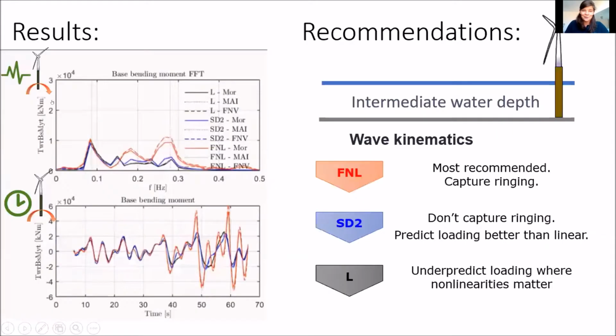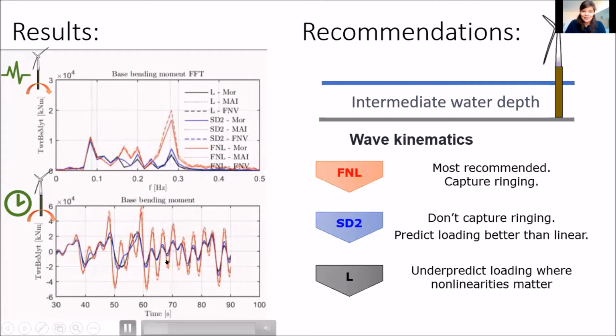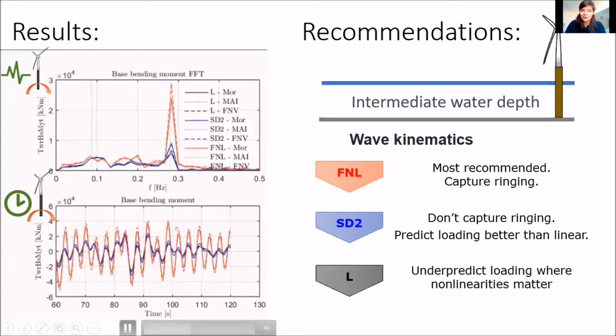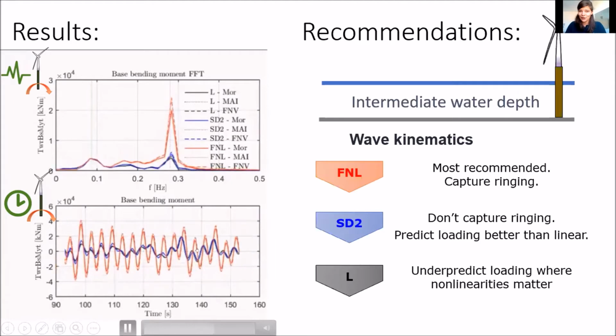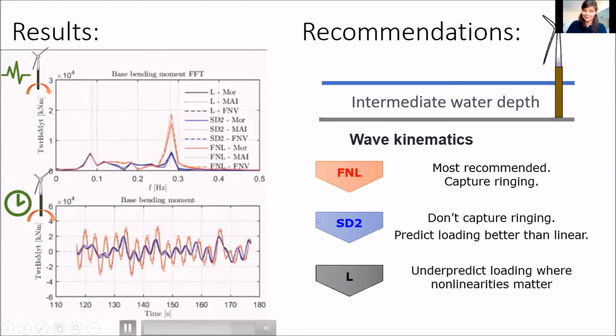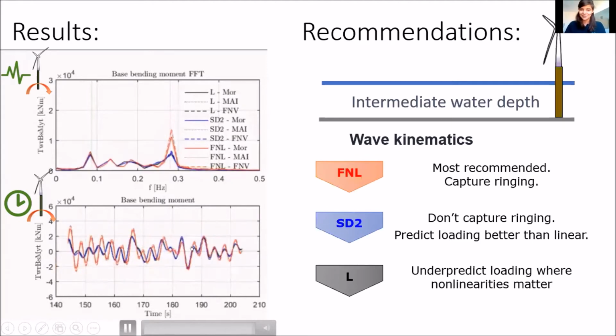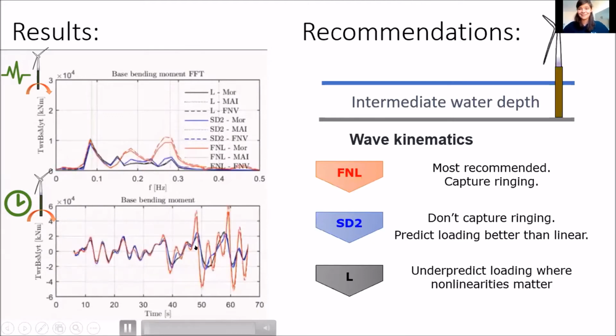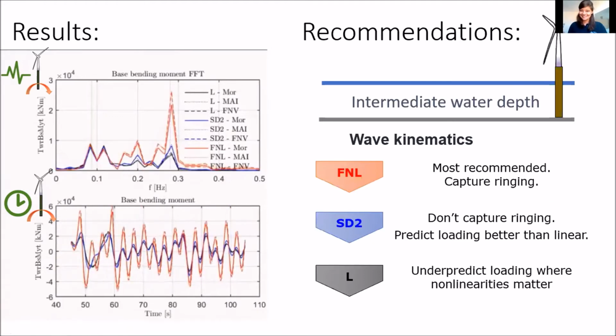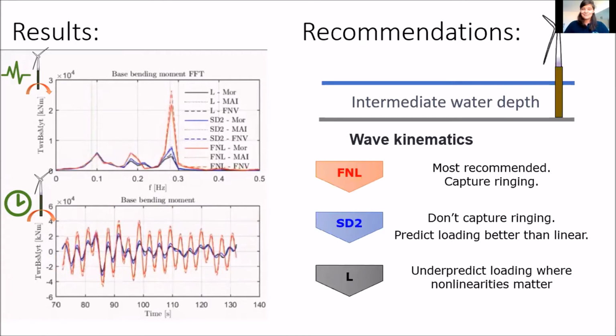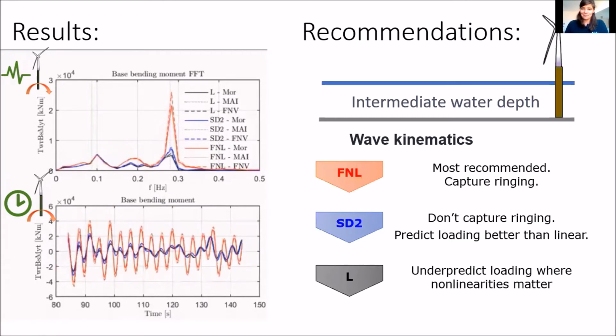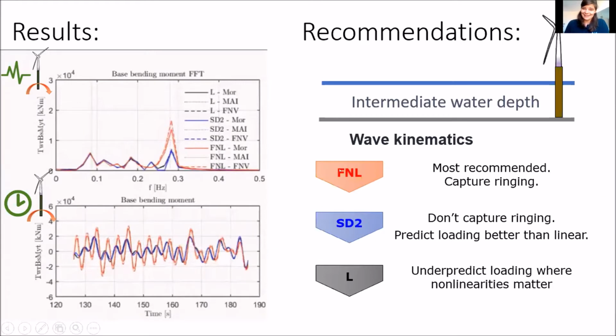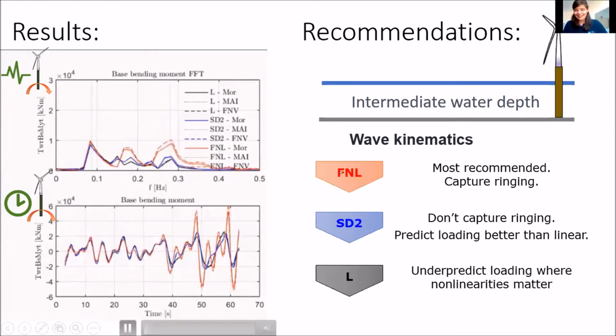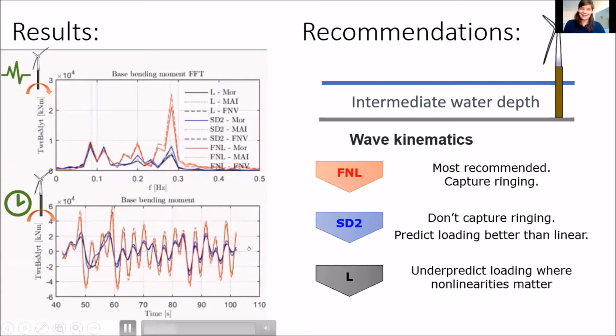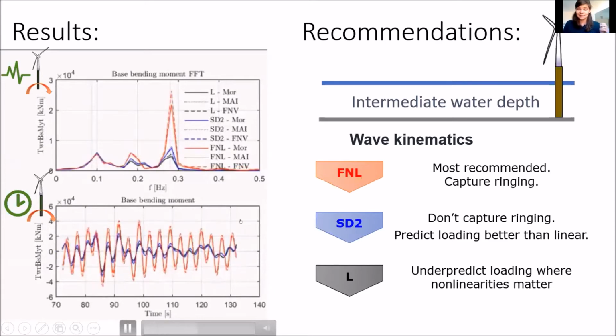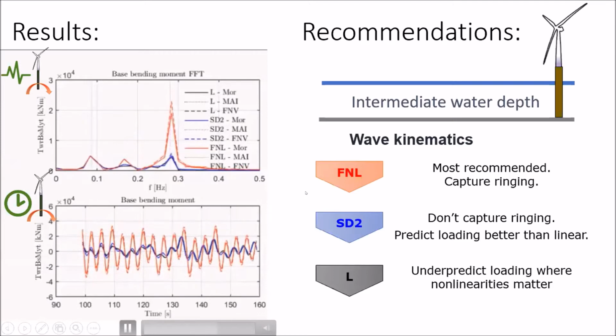And what I found was that, in fact, the amplification seen with fully nonlinear wave kinematics was not captured by the second order wave kinematics, regardless of the hydrodynamic loading model. So unfortunately, we can't optimize and say just use the second order wave kinematics, because in intermediate water depth, the nonlinearities in wave kinematics matter so much more. So I really suggest using fully nonlinear wave kinematics to capture these amplifications, this wave-induced resonance on monopile-supported offshore wind turbines.